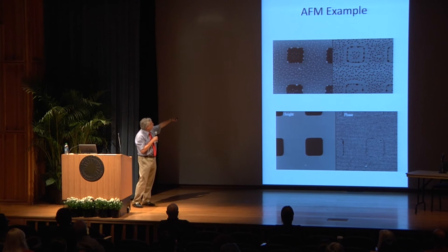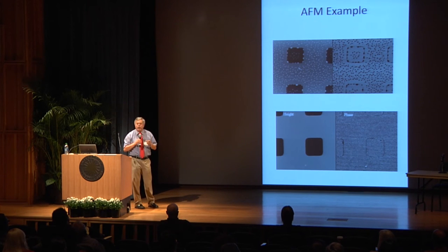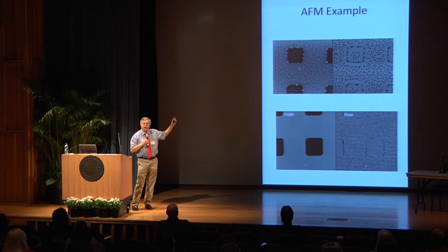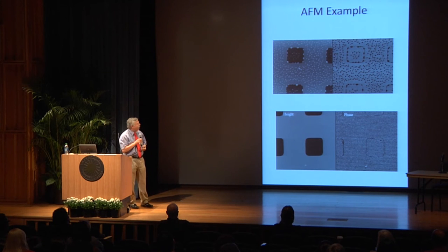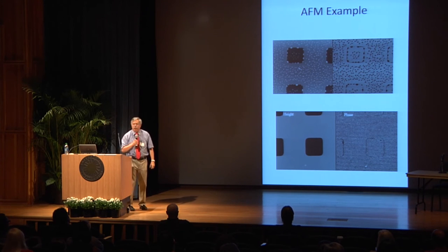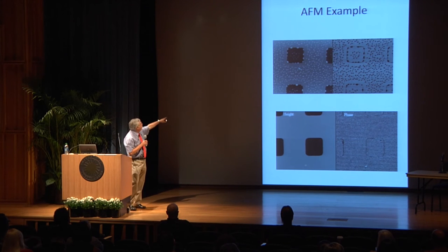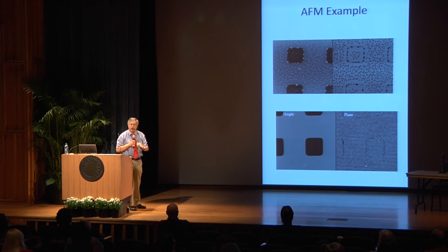So this sample is what's called a step height standard. The dark areas are deep, the brighter areas are the surface. And that height is set by NIST in Gaithersburg. They make the standard, everyone reproduces it. This was a very heavily contaminated sample, ready for the garbage. The image on the left is step height, up and down distance. Left and right distances are not accurate in this measurement, but up and down are.